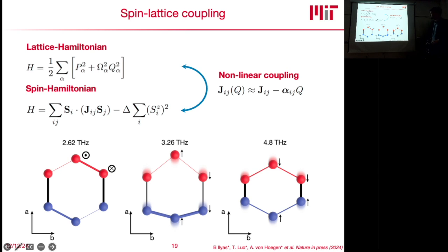What we'll find is that this mode that corresponds to the magnon-phonon, the exchange interactions on one of the chains is weakened, and on the other one it's strengthened. Whereas here only the exchange interactions between the chains are modulated, and here we get something that's called a columnar order parameter, which will also not give rise to magnetization.